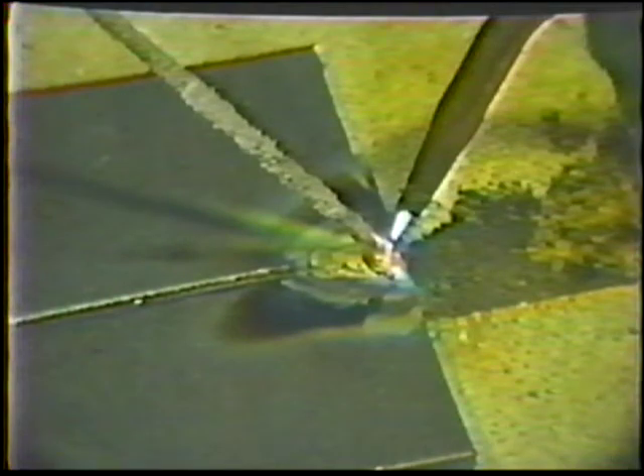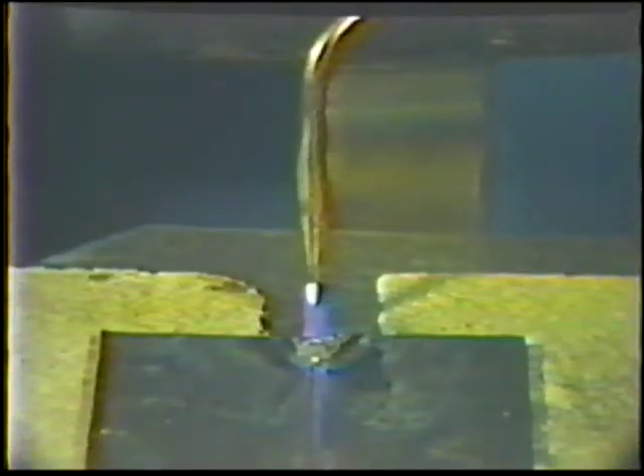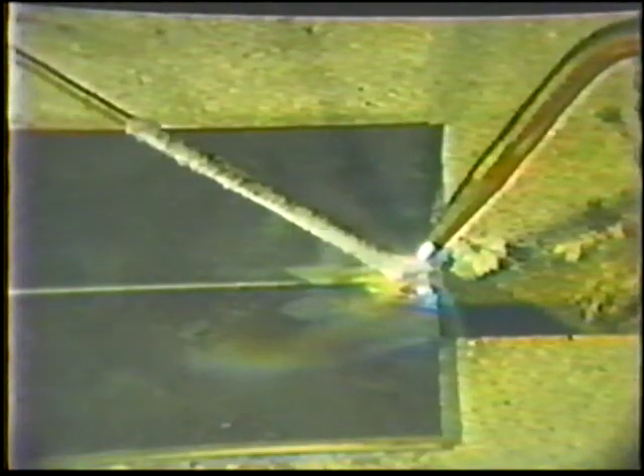Using the flux-coated rod, tack weld the 2 plates together, then place them in position on 2 fire bricks. Make the tack welds about 1/4 inch long. Use a 90-degree work angle and a 35 to 40-degree push travel angle, directing the torch on the right end of the joint. Hold the filler rod at the same angle as the torch, but in the opposite direction.